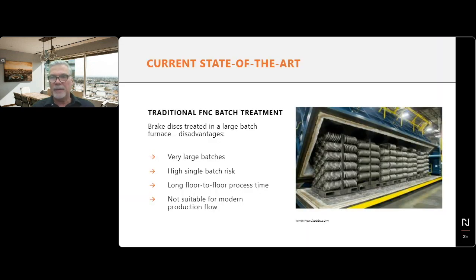Okay, so what I wanted to say basically is that once you move away from our metallurgical lab or experiments that we do here in Montreal, what you see behind me is not the real background. I am in the plant. What happens is that you have to have extremely high productivity ratios with very heavy components, of course. So you have to treat literally millions of discs every year, and all of those discs are very heavy. So you may have to maintain as well a quality of surface finish, a productivity rate, and somehow stay competitive because the automotive or transportation industry is extremely competitive.